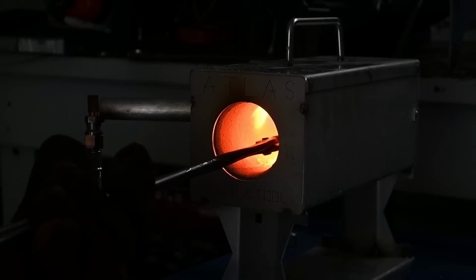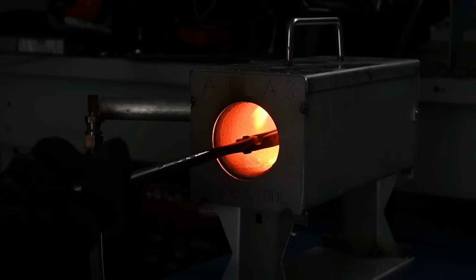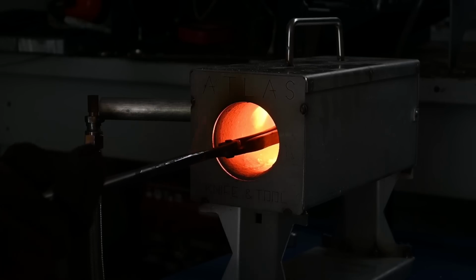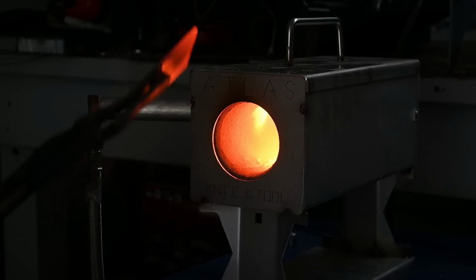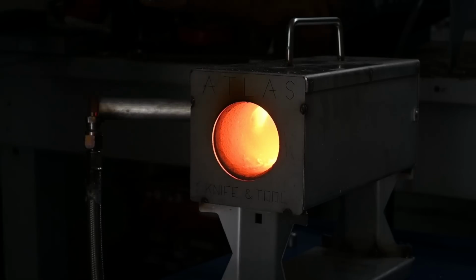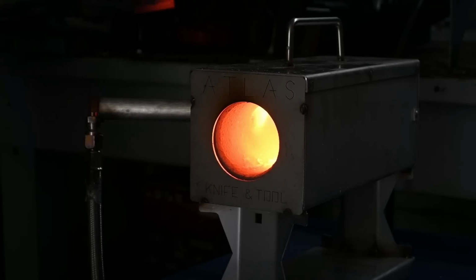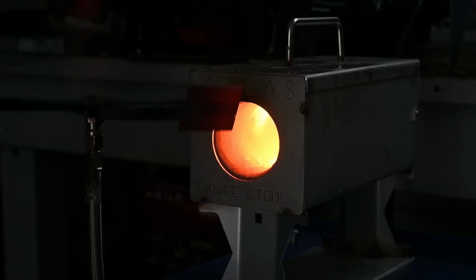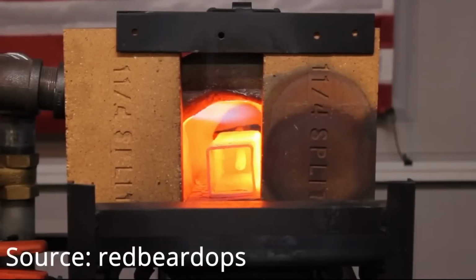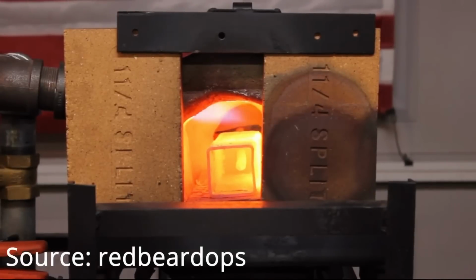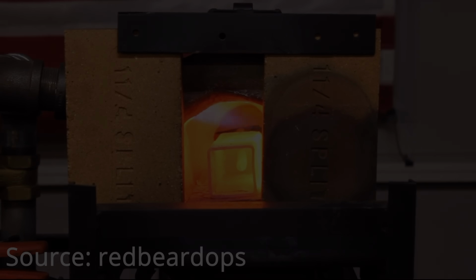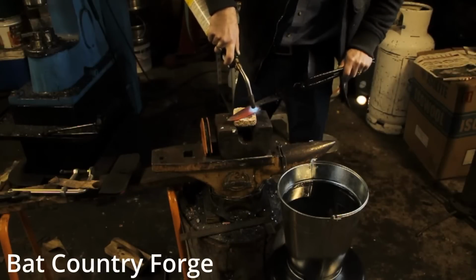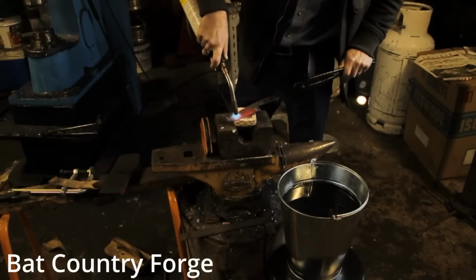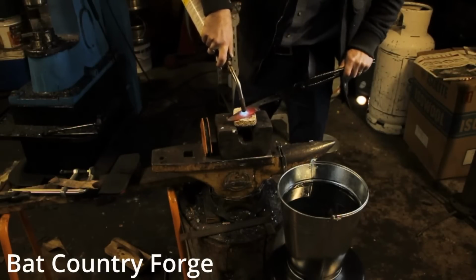Custom knife makers do not always use furnaces, however. It is relatively common for knife makers to use a forge, which is relatively uncontrolled, and the goal is to pull the blade after it is heated into the right range. Some knife makers will try to hold a specific temperature within the forge or improve the uniformity of the forge by using a baffle, also called a muffle. This can be as simple as a large piece of pipe. And less common, though still done by some, is to use a torch to heat the edge or the entire blade. Again, this is relatively uncontrolled compared with a furnace.